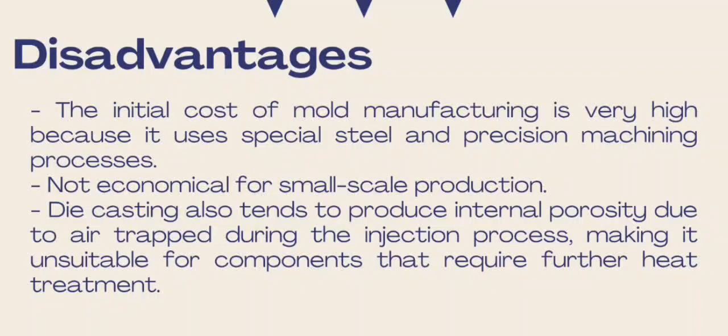The initial cost of mold manufacturing is very high because it uses special steel and precision machining processes. In addition, this method is not economical for small-scale production. Die casting also tends to produce internal porosity due to air trapped during the injection process, making it unsuitable for components that require further heat treatment.